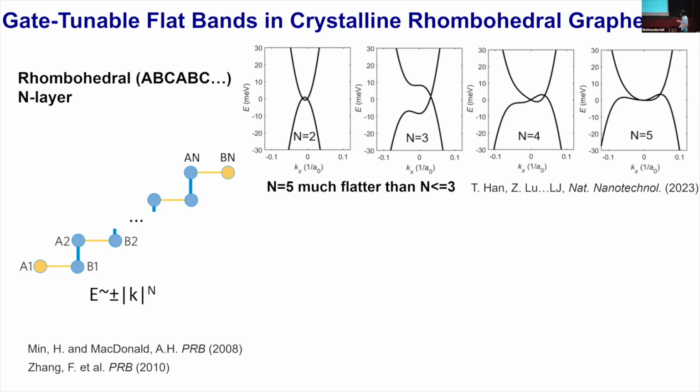And the interaction energy scale, I mean, you have to find a characteristic length. In the case of moire, roughly if you have a moire period of something like 15 nanometers, the simple e squared over L estimate gives you something like 25 meV. So it could be strong. It could be like kinetic energy is well below the interaction. Or it could be comparable. Yeah.